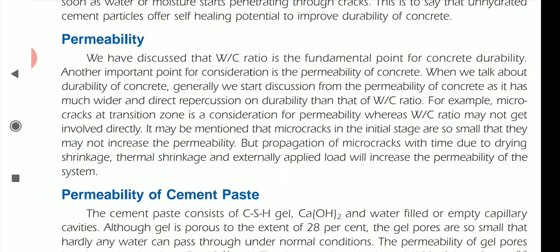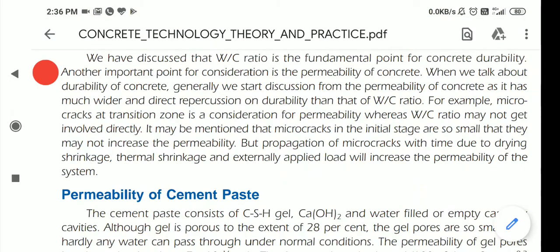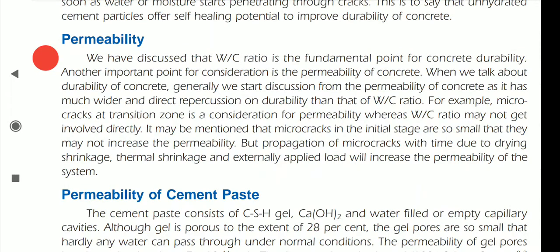For example, the micro cracks at the transition zone are considered for permeability, where water cement ratio may not get involved directly. It may be mentioned that micro cracks in the initial stage are so small that they may not increase the permeability, but propagation of micro cracks with time due to drying shrinkage, thermal shrinkage and externally applied load will increase the permeability in the system, and this will increase the cracks and reduce the durability.